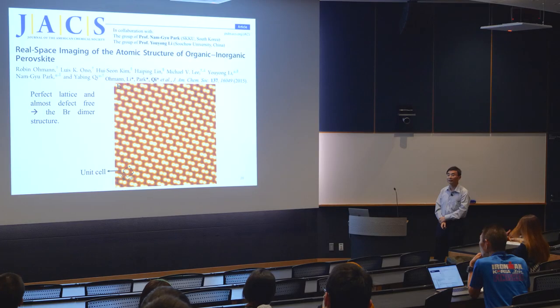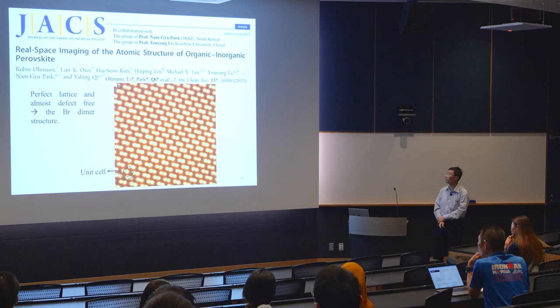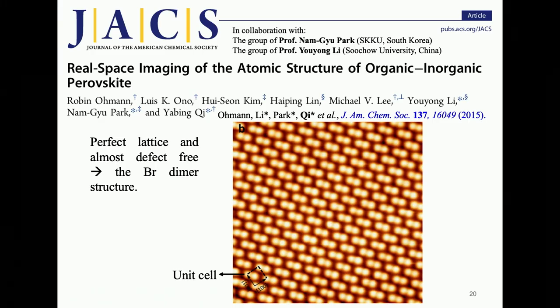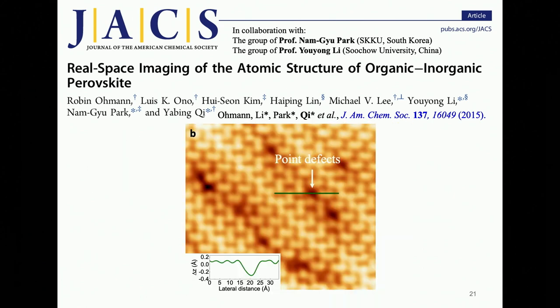So when we scanned much larger regions of the sample surface, we found many regions with perfect lattice and almost defect-free. So here in this example, we can see everywhere shows the characteristic bromine dimer structure. On the other hand, when we scanned some other regions of the sample surface, we observed defects. For example, in this image here, the dark depressions are point defects.